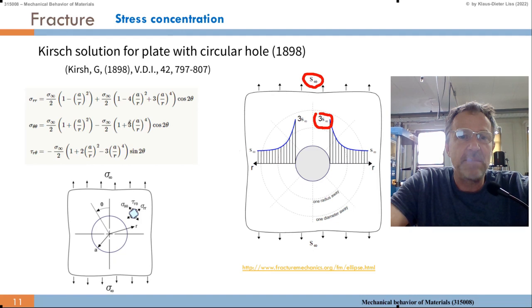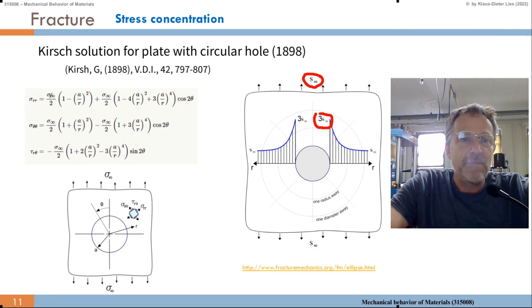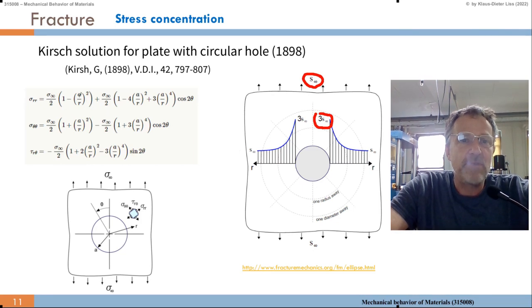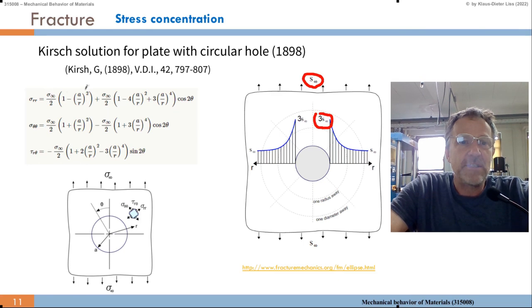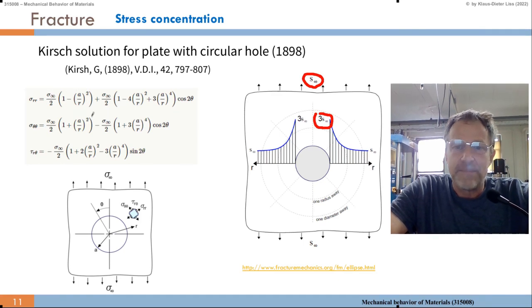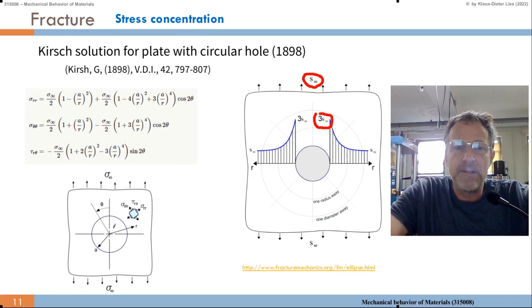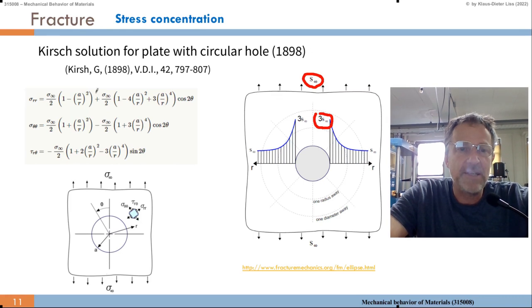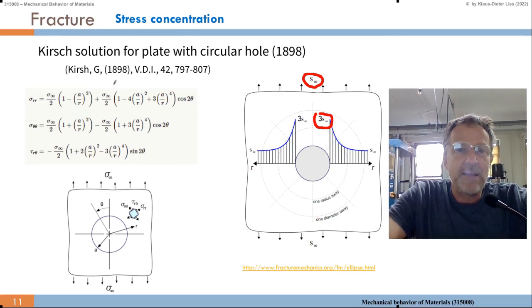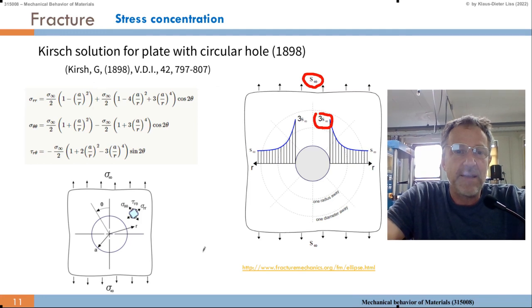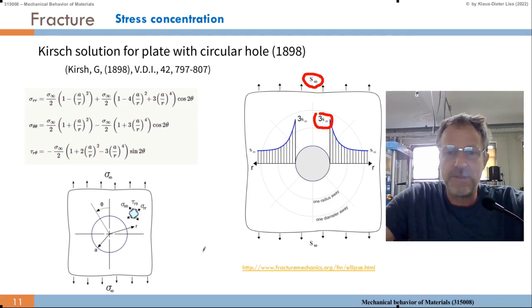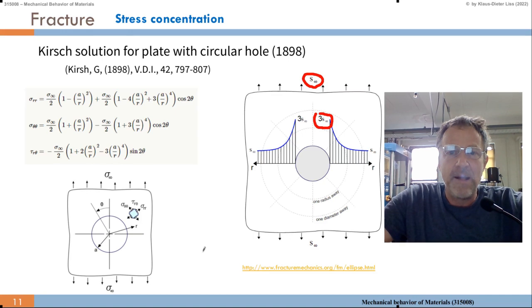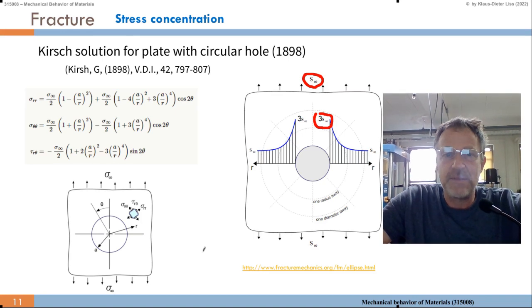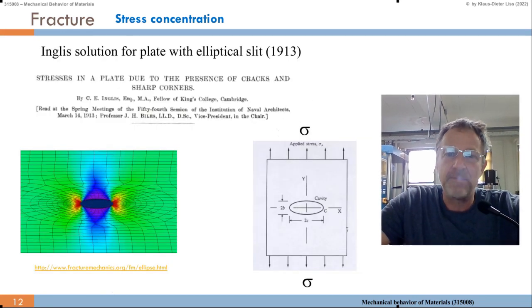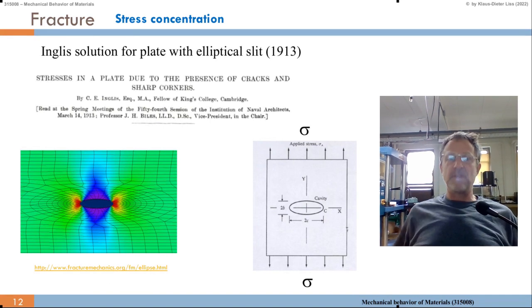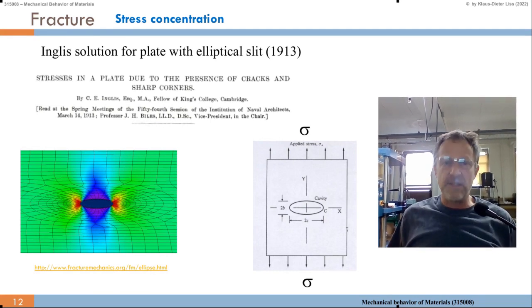We have sigma RR, which is sigma infinity over 2 times 1 minus A over R squared, where A is the radius of the hole, plus these cosine terms, as shown in the image. So the total stresses can become up to 3 times the stress applied at infinity. This is stress concentration: even if it doesn't yield at infinity, because it's concentrated, it becomes higher locally.